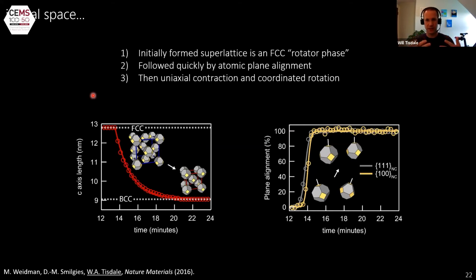Despite these oleic acid, 18-carbon disordered ligands on the surface, there is some driving force for the atomic planes on neighboring nanocrystals to form an epitaxial registry across lattice sites within the crystal. Once that atomic plane alignment is achieved, then the overall structure undergoes a uniaxial contraction and a coordinated rotation that continuously transforms the crystal from an FCC phase to a final BCC structure through a series of body-centered tetragonal intermediate